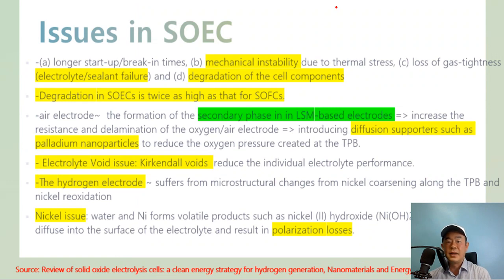So let's look at the problems SOEC has. There are longer startup and break-in times, mechanical instability due to thermal stress, electrolyte sealant failure, and degradation of cell components compared to low temperature electrolysis. It is known that the degradation of SOEC is twice as high as that for SOFC.